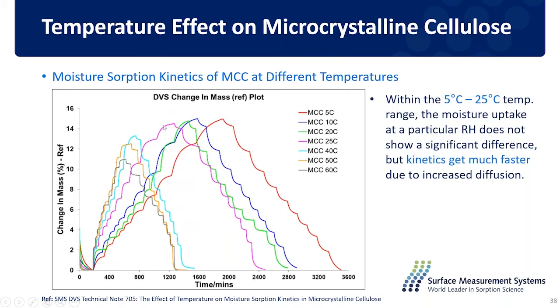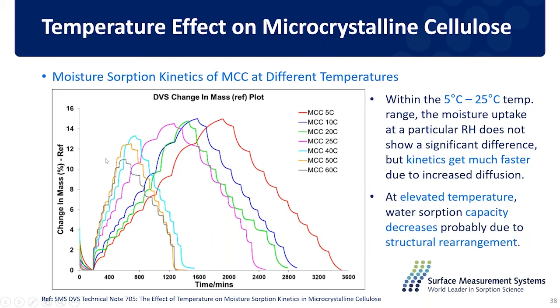At low temperature range, from 5 to 25 degrees, the uptake of the moisture sorption doesn't change significantly, but there is a significant decrease of the experimental time at 25 degrees compared to 5 degrees. So basically, with increasing temperature, the kinetics of this moisture sorption increase a lot. And then at higher temperature range, with elevated temperature, this time the moisture sorption kinetics and capacity decrease a lot with increasing temperature. This is probably due to the structural change of the material at higher temperature.